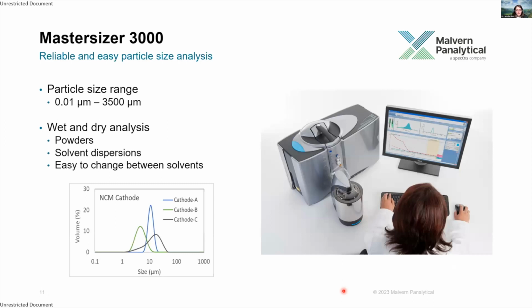So the Mastersizer 3000 is the world's leading particle size analyzer for rapid and reliable particle size measurements. It covers a very wide particle size range, so we can go from 10 nanometers up to 3.5 millimeters, and this uses a single optical measurement path. Both wet and dry analysis modes are available, so this means that we're able to measure powders, dispersions, and emulsions, and it also has excellent chemical compatibility, which allows us to handle solvents such as NMP.